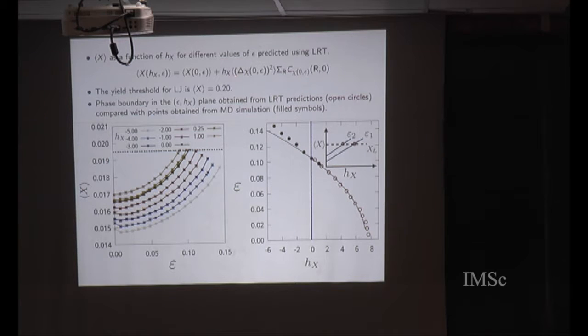One can do linear response theory to find out how this quantity changes as a function of h. And linear response, as we know, depends on fluctuation terms which are calculated for h equal to 0. So suppose you have a colloidal solid, without putting in any field, you calculate some susceptibility, some fluctuations, and these are easily accessible from particle coordinates and so on. And then you can predict what the value would have been if I were to apply a field h. Okay. Add to that one single criterion, which is the value of x at the saddle point.